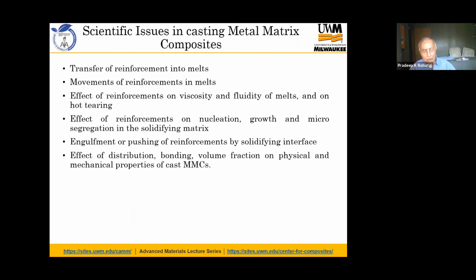I have only 25 minutes, so not much time to get into the scientific issues, but there are several. Transfer of reinforcements into the metal. We have worked out the thermodynamics and kinetics of this that allows us to calculate the kind of impellers and ultrasonic energy and pressure that you need to make these metal matrix composites. Movement of reinforcement in melts. Effect of reinforcements on viscosity and fluidity of metal melts and on the hot tearing tendencies. The effect of reinforcements on nucleation, growth and microsegregation of solidifying matrices, and engulfment and pushing of ceramic reinforcements by solidifying interfaces. And of course, effect of distribution, bonding, volume fraction on the physical and mechanical properties.